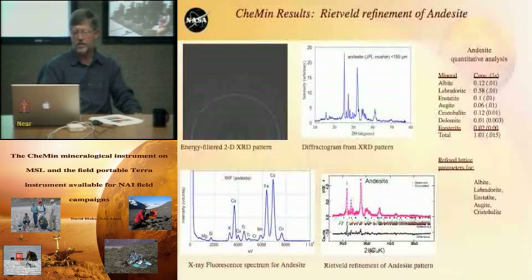You can also get, for anything more than about 10% composition, refined lattice parameters. And with refined lattice parameters, with things like olivines, you can tell the iron-magnesium ratio and so forth. And then here's the X-ray fluorescence pattern from this sample. This particular camera had a bit of iron contamination. We won't really have that issue on MSL, but that's what a standard data set will look like.